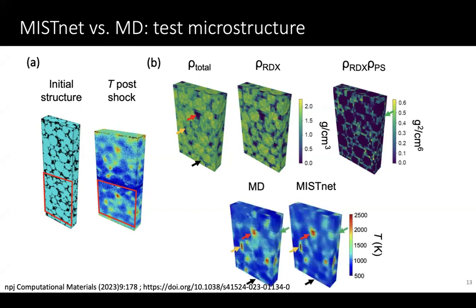And so this is what the MD result shows, and this is what the model predicts, okay? You can see it's almost identical, okay? It predicts where the hottest void is going to be. It predicts this other hotspot that's important. This guy that's oriented, it's there. It's a little weaker because it's not aligned with the shock direction, so it becomes a little weaker. This interface, there's no pore there, no significant pore, it lights up.